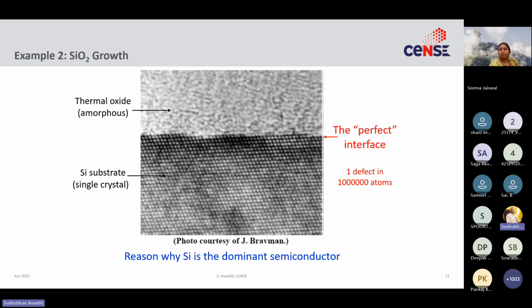And that is rare and surprising because the silicon dioxide that we are talking about is actually not crystalline, it's amorphous. So the stuff that you see on the top, you don't see any structure because that silicon dioxide is amorphous. On the bottom is crystalline silicon, which has the perfect silicon lattice that I just showed you. Now you can assert that clearly at the interface, some shenanigans must happen because this is amorphous, this is crystalline. Clearly, there must be defects at the interface. And there could be some defects at the interface in terms of structural defects, but when you actually go and measure them electronically, we actually don't find any. And this is one of the reasons why the silicon dioxide interface is probably the most important commercial interface in the world.